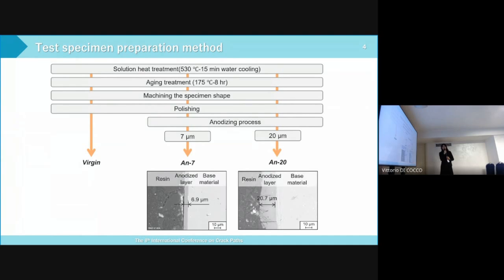We prepared three types of specimen. Solution heat treatment and aging treatment were performed on a round bar. The round bar was machined into the specimen shape, and the test section was polished. Hereafter, this will be referred to as virgin. Next, two types of anodized specimen, with thicknesses of 7 micrometers and 20 micrometers, were prepared. These specimens were referred to as AN7 and AN20.